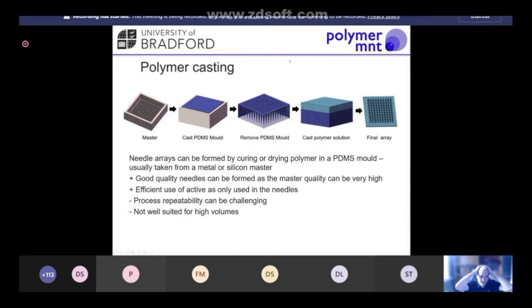A very, very popular method of microneedle production, so of producing some of the bioabsorbable or dissolvable microneedles that I showed earlier, uses a technique called polymer casting. The way polymer casting works is we can take a master, that could be our silicon-based master from the slide I showed before, where you get these really high-quality silicon microneedles, and then you can basically cover that in a PDMS, a silicone mold material. By immersing that microneedle array in a PDMS mold, letting that cure in position and then removing it, you're effectively creating a mold for those microneedle geometries.